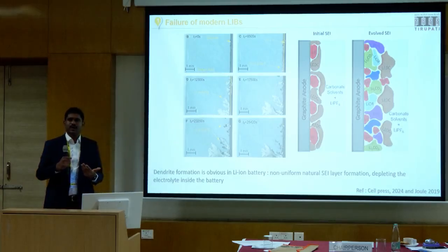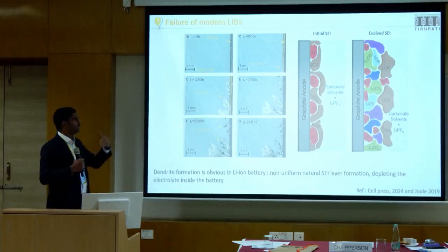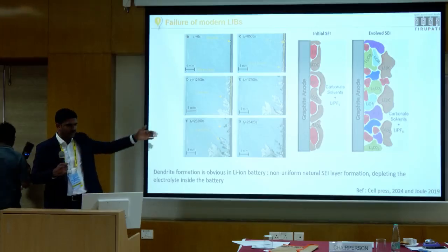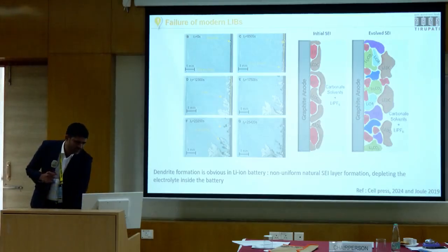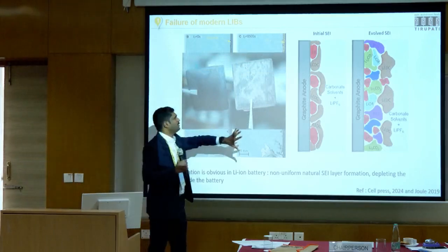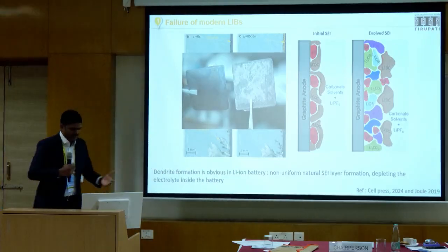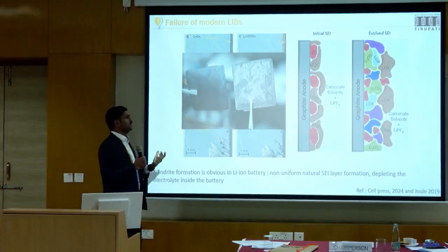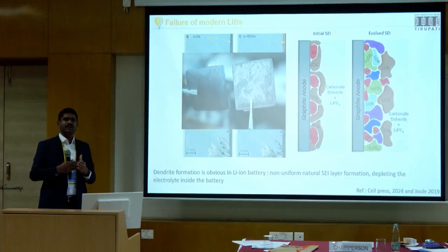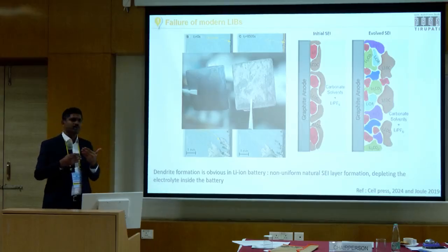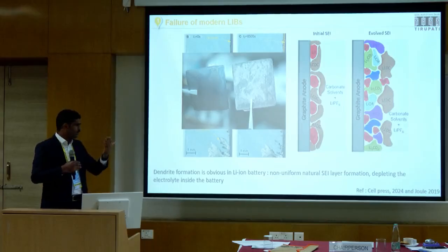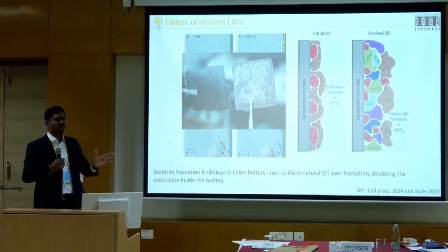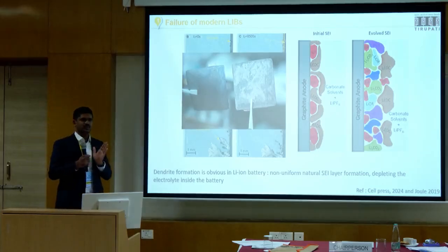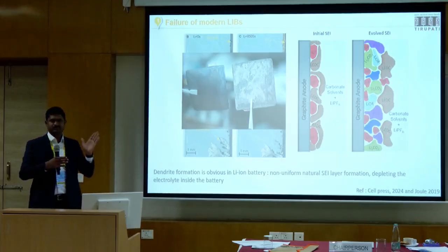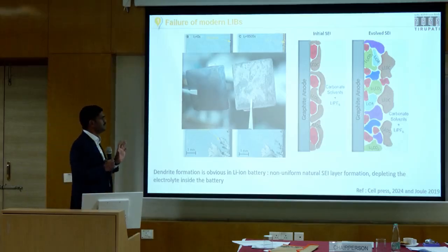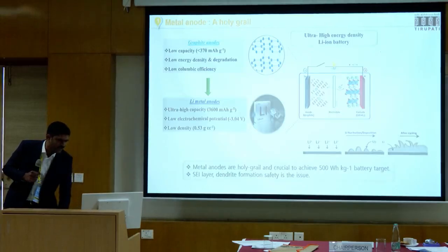Even with the modern rechargeable battery, the mode of failure is an internal short circuit, mainly by dendrites. And why these dendrites happen is due to improper SEI layer formation. I will not go deep into the science, but the understanding is about the naturally formed SEI layer. The moment you fabricate the battery, a native layer forms inside the battery so that it helps the battery to run longer. But the naturally formed SEI layer is not smooth, so it needs a sophisticated technique to make it smoother and thinner, and this is not happening in any battery. That's why the failure of the battery is happening.